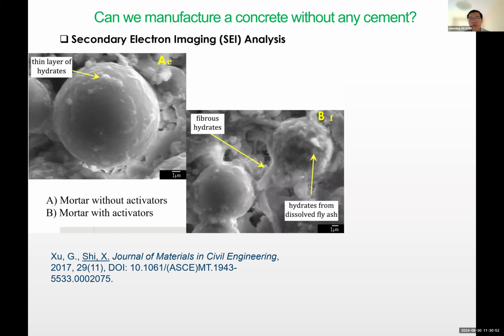So the question then becomes, can we manufacture a concrete without any cement? So we were playing with this Class C ash, which is fly ash. Typically, the classifications include Class C, Class F, and Class N. Class N stands for those naturally occurring. But for the industrial byproducts, Class C stands for those that tend to have higher calcium oxide content, and Class F is those with higher silicon oxide content. So this Class C ash, without any activator, when we mix it with water at the water-to-ash ratio of 0.3, you actually get some strength. That's the figure on the left.